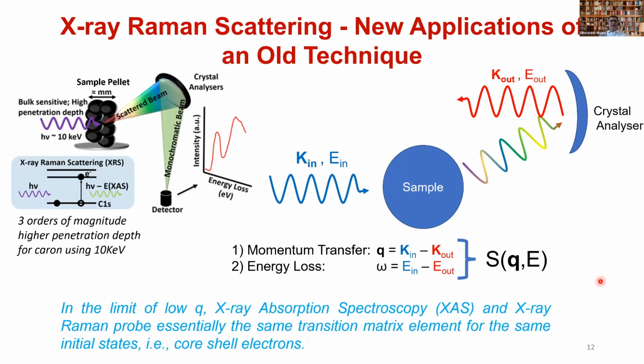this technique is not limited to low Q. You can also go to high Qs, and you get a lot of other information there as well. However, for our purposes, we have limited ourselves mostly to low Q, because what we are really interested in is getting the same information that NEXAFS can give us, but not just from the surface. So we want to be bulk sensitive, because we are trying to develop a lot of materials, for which it is very important to understand the bulk properties.